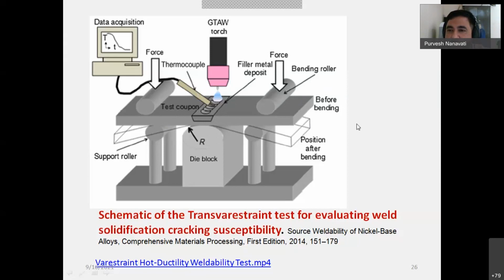So what will happen when we apply force from both? This will produce cracks not only in the fusion zone, but in the heat affected zone as well. And you would see that thermocouples are attached here. Using the thermocouples, we can also measure the time for solidification, from TL to TS, from the liquidus temperature to the solidus temperature. So we can find more accurately under what temperature fall, from liquidus to solidus temperature, the crack will develop. So these are the latest developments in the basic Varestraint test. This is the transverse test.